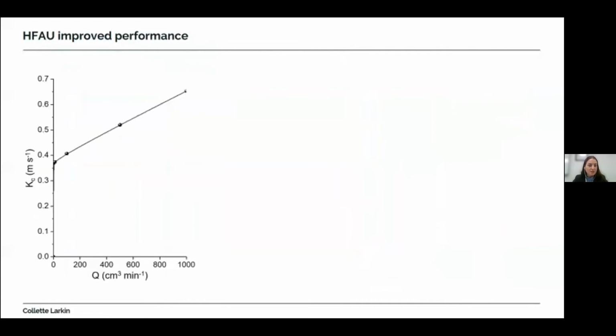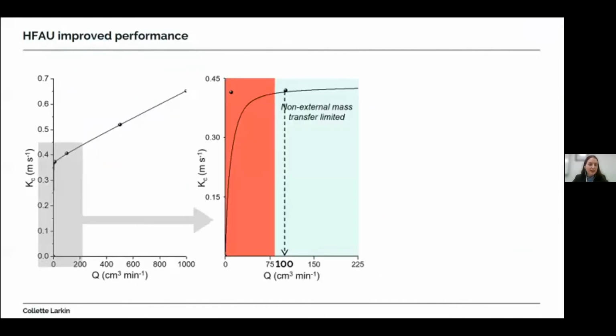So to understand why the mass transfer resistances inside the hollow fibre adsorption unit are minimised, computational fluid dynamics simulations using CFD were undertaken at 5 different volumetric flow rates. From the simulations, a plot of mass transfer coefficient against volumetric flow rate was obtained, as shown, to assess the external mass transfer limitations of a hollow fibre adsorption unit. Zooming in on the grey area, it can be seen that at our feed flow rate of 100 centimetres cubed per minute, the diffusion of CO2 is not externally mass transfer limited.